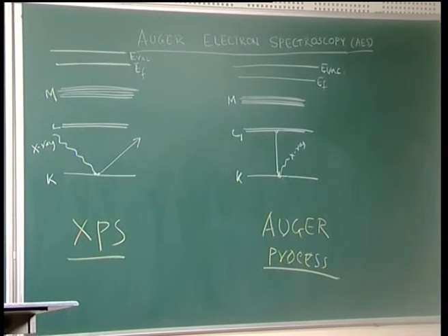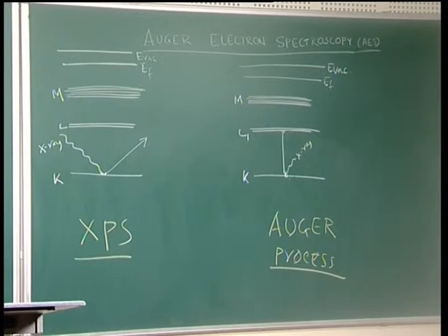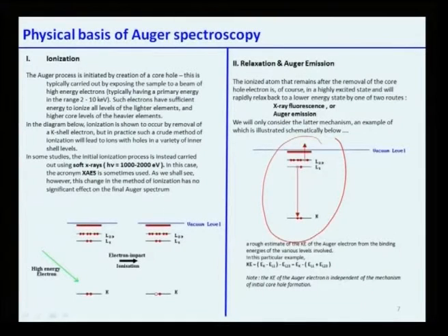So what is done here is as follows, which can be seen from this picture very carefully. What I have drawn here and what I am showing in the slide is similar. Because a hole is created in the K level as the electron has gone out, one electron from the L1 level will jump and fill the hole, and because of this some energy is released, and this energy can then eject an electron from, suppose, the L23 shell, and this is what is known as Auger electrons.